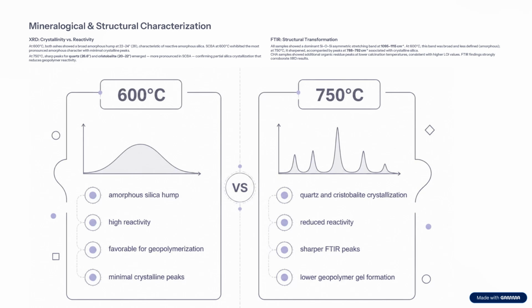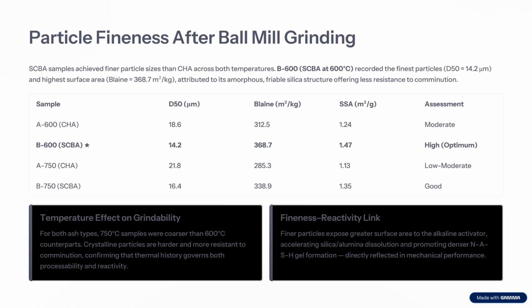For comparison, at 600 centigrade we have amorphous silica, higher reactivity, favorable for geopolymerization, and minimum crystalline peaks. 750 centigrade shows quartz and cristobalite crystallization, reduced reactivity, sharper FTIR peaks, and lower geopolymerization.